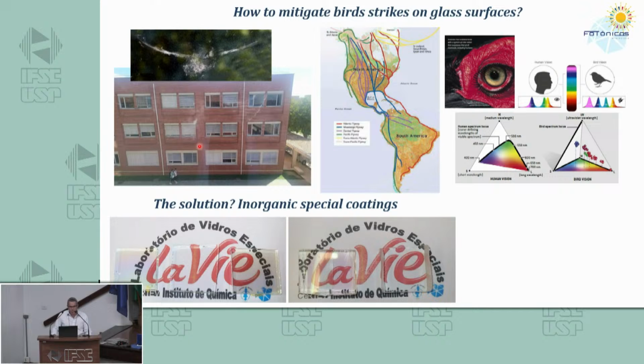So we did some studies here, and we developed a coating, an inorganic coating that can be produced by sputtering. You remember sputtering that I told you about in the beginning? That is the same technique used by industry to deposit titanium oxide and make the intelligent glass, the self-cleaning glass. Okay, self-cleaning glass is prepared with a sheet of glass and a coating of titanium oxide on the surface. There are many other properties related to them.